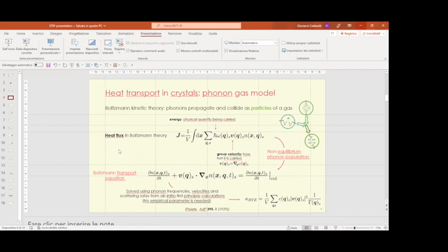No, it's calculated ab initio. Well, there are some software implementations where you can compute, from a supercell approach, the third order force constant matrices. So the first order expansion after the harmonic approximation, you can compute the third order force constants between atoms, and from that you can obtain the... And do you have in your slides a formula showing how these third order matrix elements enter into play in the self-energy? No, I don't have a slide, but it's basically computed at the lowest perturbative order. So it's basically a Fermi golden rule for the anharmonic interaction Hamiltonian.